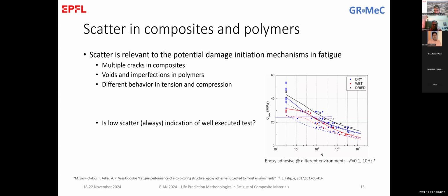Suppose we conduct more tests in the dried state, then we might get a similar scatter and the curve can go up or go down. So at this stress level, how can we conclude? Yes, I'm talking about this. At this stress level, the blue data for me are not in a good format, or to say it in a different way, this is a scatter that for me is too large. If I see this data, I would think that something special happened at least with this point here, with this specimen, and this specimen failed prematurely.